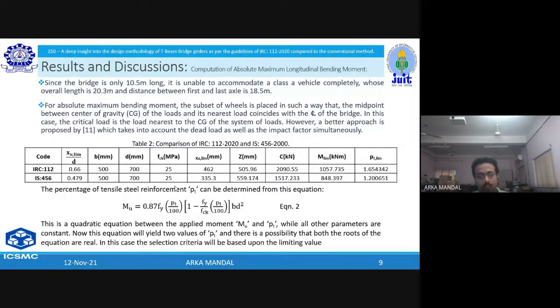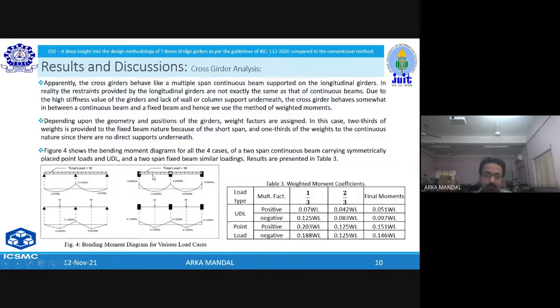Now, we generally determine percentage of steel using a quadratic equation as shown in equation number 2. Since this is a quadratic equation, this will evaluate two roots, and there is a high chance that both the roots are real. In many cases, it has been seen that the greater value of the root, which is greater than the limiting percentage of steel, is considered. In that case, the section design is severely over reinforced, and that might cause problems. So we should always perform the limiting percentage of steel check.